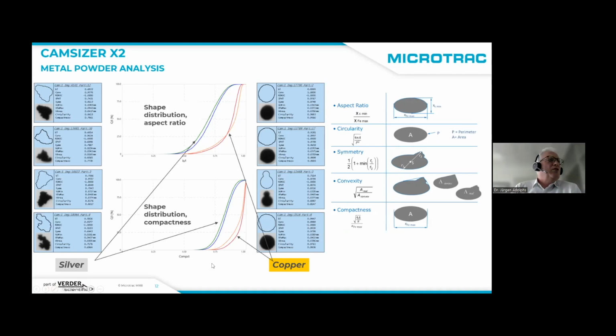And again, we now see a much bigger difference when we use, for example, the aspect ratio as a measure to characterize the particle between the silver, which is here much higher, less than 1. 1 would be a perfect sphere, compared to the copper, which is approaching the value of 1. Or when we look at the compactness, we also see differences between the silver and the copper.